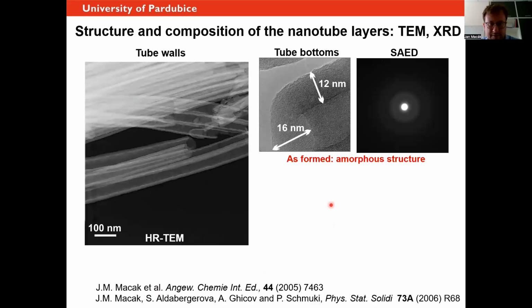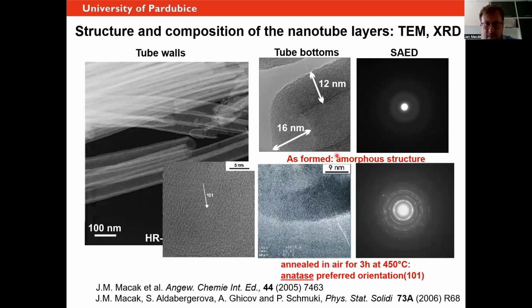So for those who are not yet necessarily familiar with this material, titanium nanotubes always grow amorphous. So when you do the anodization, no matter what you do, you will have always amorphous structures. So if you do XRD, TEM, you see no crystals. If you anneal it in air, you can also take other atmospheres, but typically air, it's the easiest, you will get, depending on the temperature, anatase or rutile, or mixture of anatase and rutile, right? So you can see you have this typical 101 anatase structure.